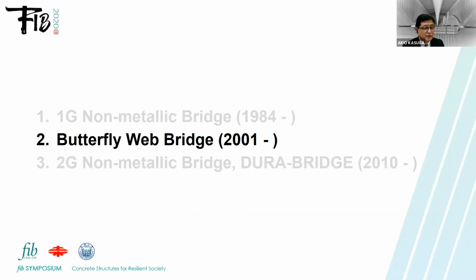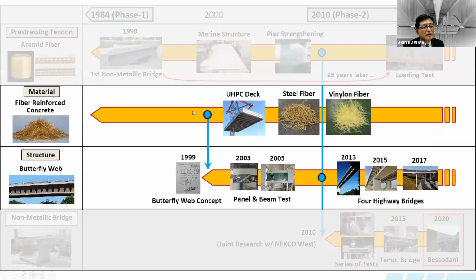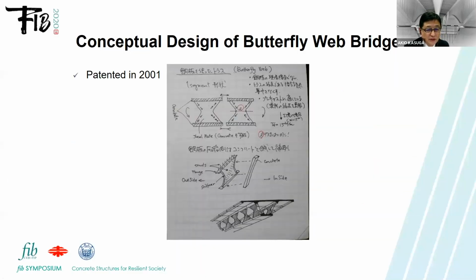Okay, after the suspending of the first generation, the new structure come, which is butterfly bridge from 2001. This helps a lot for going to the next generation. So at that time, around 2000 years, we have very, very good materials, fiber reinforced concrete in the practical field. And also from 2000 up to 2013, we built the very, very new butterfly web structure, which leads to the lighter superstructure to reduce the concrete, because this kind of new concrete is more expensive than the ordinary concrete material. I'll show you the detail.